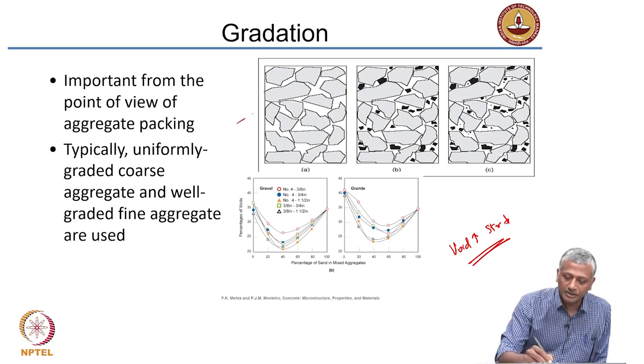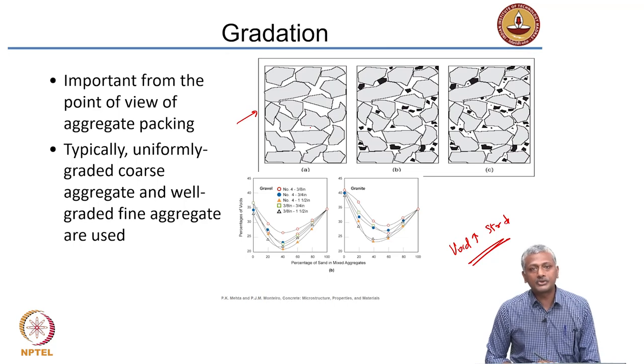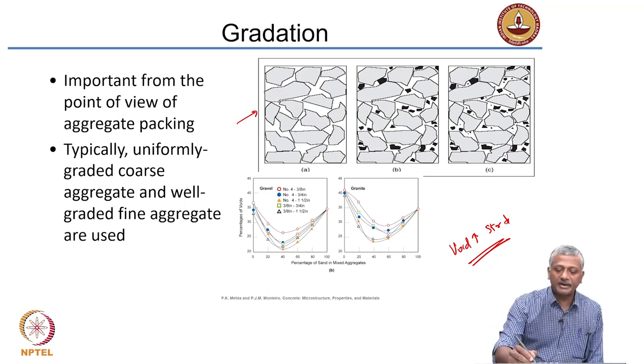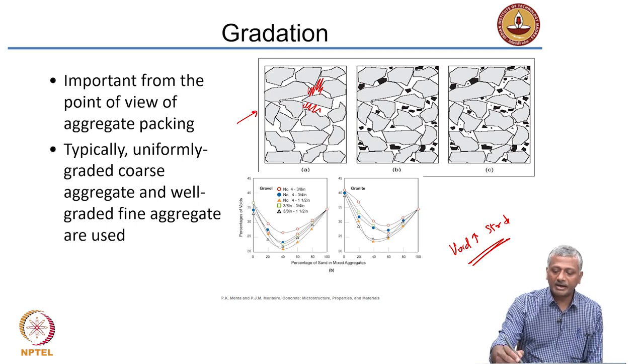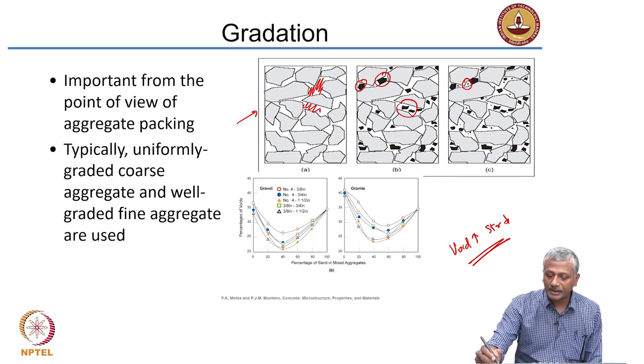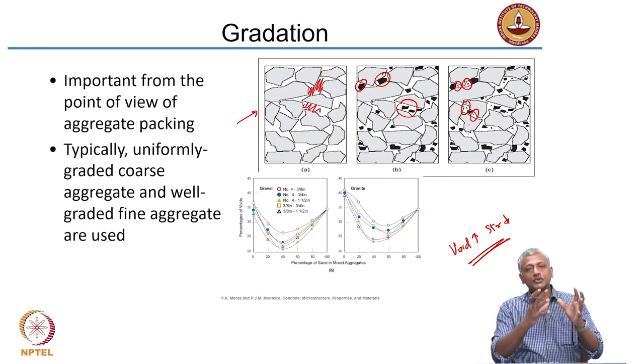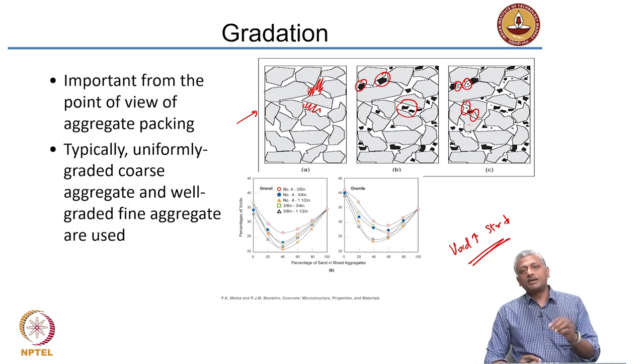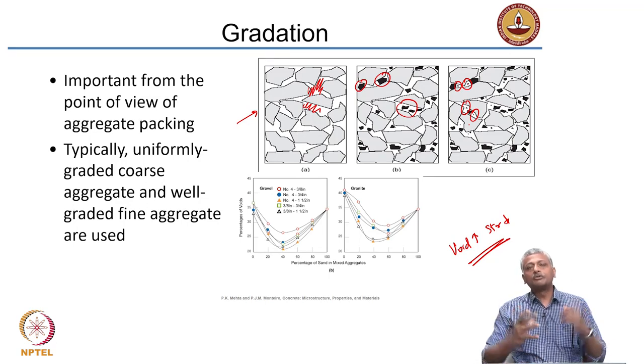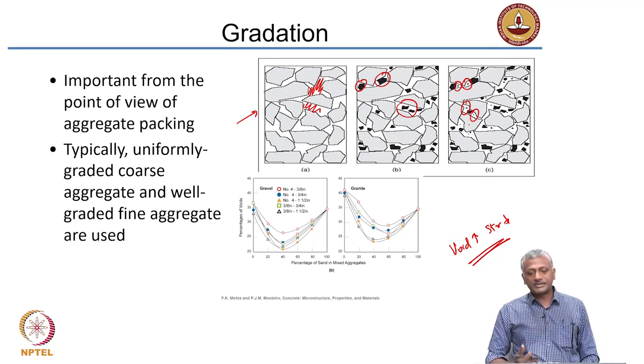To reduce voids, the best thing is to use materials in concrete which follow a gradation that fills up the gaps left behind by the larger particle sizes. You have coarser aggregates which leave behind voids; then you choose another size of aggregate that fills up those smaller voids; then even smaller aggregates fill the remaining voids. You choose your gradation so that you maximize the filling of the volume, getting a composite with the least void content.